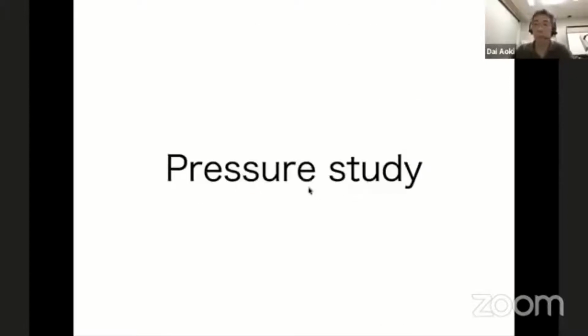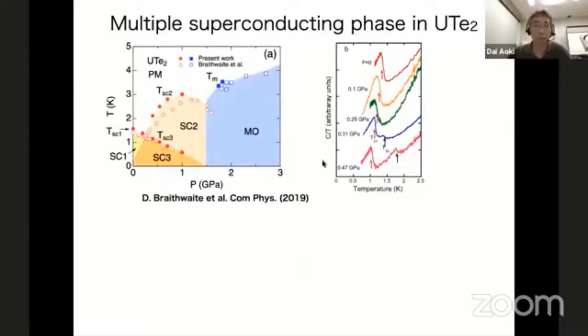Okay, so now I want to show you the pressure study. The pressure study is also very interesting in this material. This is the temperature-pressure phase diagram. Here you can see at ambient pressure it's 1.6 Kelvin. Then applying pressure, first TC decreases, then it splits at 0.25 gigapascal. There are two transitions, and these two transitions are measured by specific heat, AC calorimetry. Basically it's a thermodynamic response, so this is a bulk property. You can see at 0.3 gigapascal, for example, already the double transition, and at 0.47 it's rather clear. Then above 1.5 GPa, the superconductivity is suppressed.